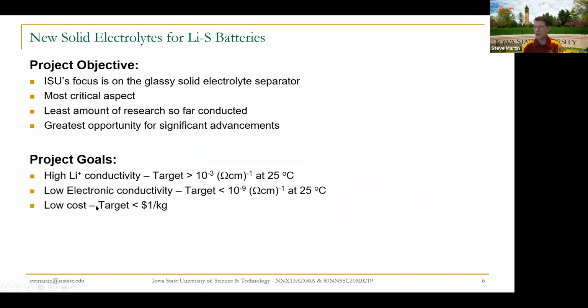We have all kinds of targets. Sometimes they're involved with cost. Lithium ion conductivity is really important because the faster the lithium ions move, the more current we can draw from the battery, and the faster our automobile can travel. There has to be a very low electronic conductivity, because if you have electronic conductivity through the electrolyte, that'll short circuit the battery, or more likely, it just drains the battery. The shelf life of the battery decreases with time.